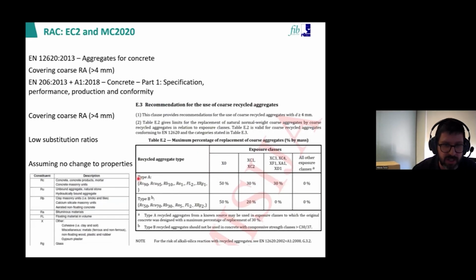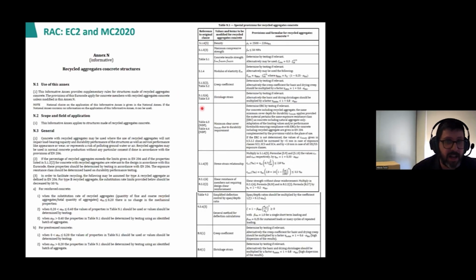The important thing here is that this, for us, classifies the types of recycled aggregate, type A and type B, or type 1 and type 2. Type A being recycled concrete aggregate, so almost pure concrete waste, and type B being what we call mixed recycled aggregate, containing also masonry up to 30%. So let's say less stiff, more water absorption, and so on. And so this is basically Annex N.